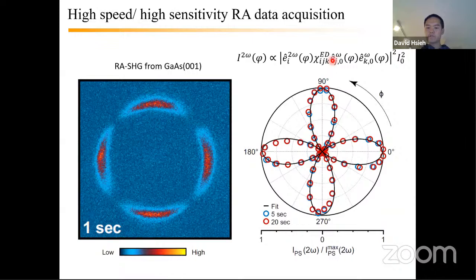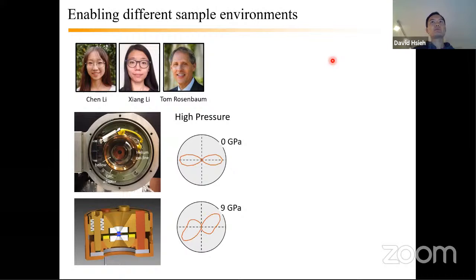So just over the past year or two, we've been trying to work towards this promise of being able to do these things under extreme environments. We've recently realized the ability to take data under high pressures. We have a diamond anvil cell that can go up to 30 GPa or so, and we're able to take these rotational anisotropy patterns under high pressures. Here's an example of a structural phase transition occurring as a function of pressure in a Weyl semimetal. And this is done in collaboration with Tom Rosenbaum's group at Caltech, who offers a lot of high pressure expertise.